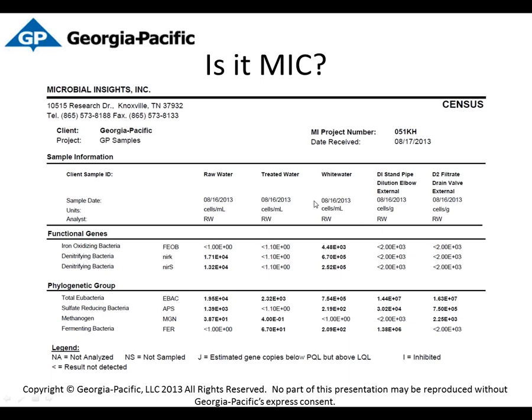After we didn't find much of the high concentrations the previous slide showed, we went back and looked at other forms of bacteria in our system. And one of the higher ones we found were the denitrifying bacteria. You see some of the highest counts were in the raw water and the white water. Again, the sulfate-reducing bacteria remained relatively low until you get over here to some of the filtrate lines. We saw a little bit higher concentration there. And fermenting bacteria were one of the highest here in the standpipe and some of the filtrate.